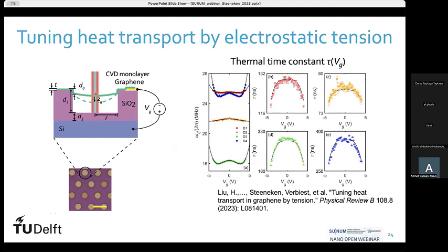So we applied the gate voltage on the membrane, so we pulled it down. And we saw here also that the resonance frequency was increasing when we were doing that. You see it, especially on the blue and the green, that the resonance frequency started increasing. At the same time, we measured this thermal time constant, and we saw that it was decreasing when we did this. So this looked like the hypothesis worked. So we could increase the speed of heat transport by tensioning the graphene membrane.